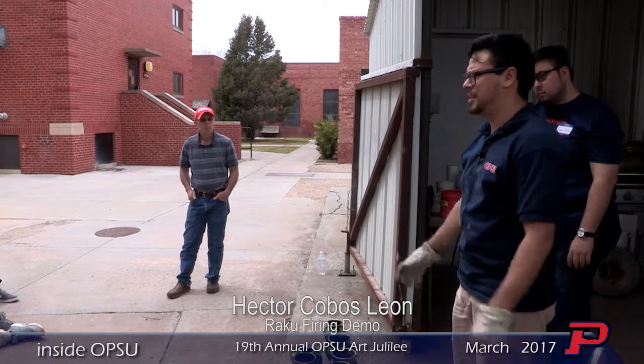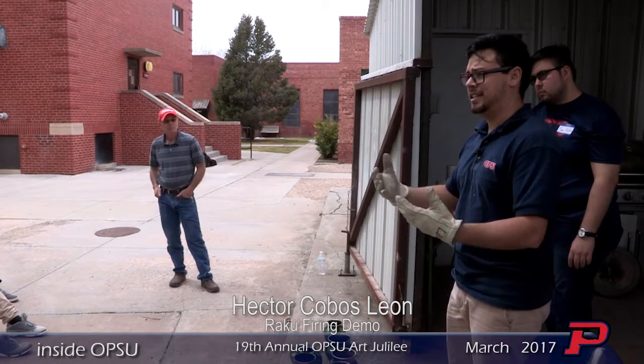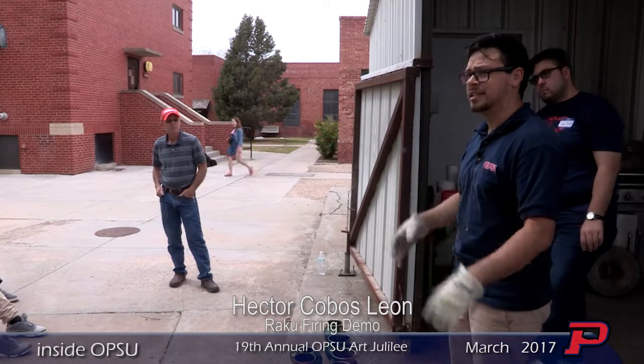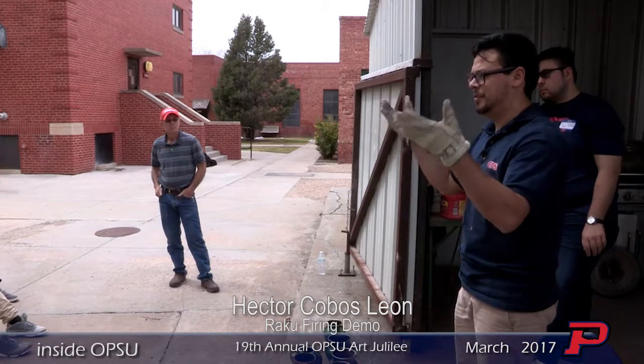I think we have 20 plus shelves that are 2x2. They stack, they're paper thin, advancers. They reflect heat. Instead of bricks, soft or hard, we have fiber, which reflects heat. So that's how we can get 100 cubic feet up from room temperature to 2400 degrees within 9 hours.